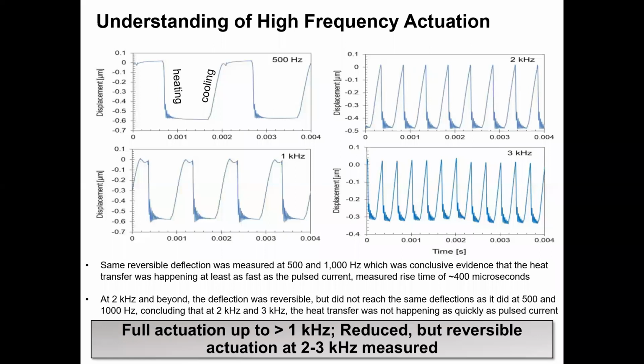At 2 and 3 kilohertz, this deflection becomes progressively less, and this is due to the heat not being fully input or fully removed at these higher operating frequencies. At 2 kilohertz, the max deflection had reduced from about 550 down to about 490 nanometers. And at 3 kilohertz, the max deflection was only about 300 nanometers. Based on these characterizations, a rise time of approximately 400 microseconds was determined during a full heating actuation cycle. At these higher frequencies, most likely only a partial shape memory effect was being induced, by heating and cooling through a smaller temperature range within the SMA hysteresis loop.